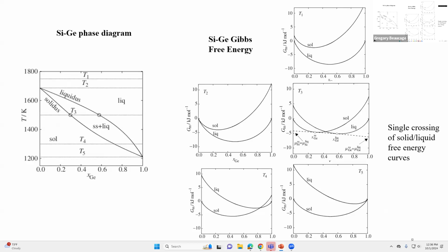Anyway, people do things. So I went through this. Each one's a Hildebrand, and then you can map out the chemical potentials, where the slope of the free energy curve gives you the chemical potential. If two phases have the same chemical potential, you map out those points on a temperature composition plot, and you can make the phase diagram. So if you have the Hildebrand equation, you can get the phase diagram.